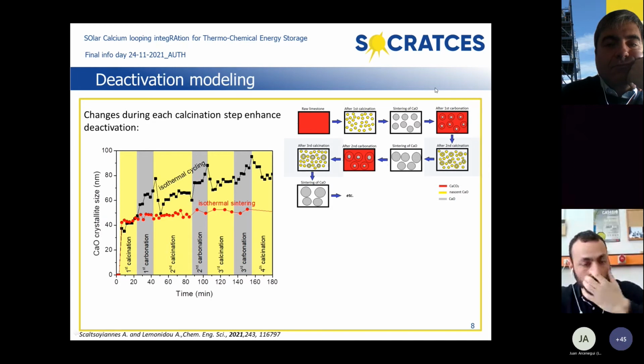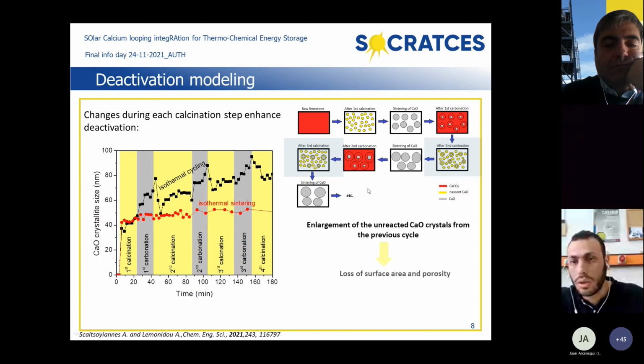And in this scheme, you can see why this happens. Because after each carbonation step, a portion of calcium oxide remains unreacted, and this acts as a surface for crystallization of the newly formed calcium oxide after the next calcination step. So this phenomenon leads to the enlargement of the unreacted calcium oxide crystals and the loss of surface area and porosity, so the deactivation of the material.